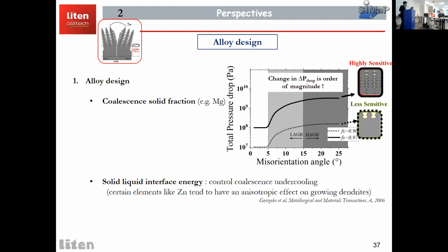The second interesting parameter is the solid liquid interface energy. We know that this parameter is able to control the coalescence undercooling, and this is how it can affect the cracking occurring at high angle grain boundaries. So for example, it is reported in literature that solid liquid interface energy can have an effect on the growing dendrites, like it can have an effect on the anisotropy of the growing dendrites and change their particular orientation. For example, zinc is reported to have an effect on the solid liquid interface energy. So further research efforts are needed to take that into account and identify which elements can control solid liquid interface energy.